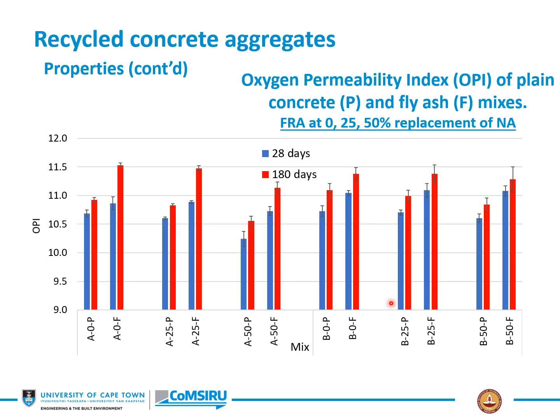If we then look at the OPI, or the oxygen permeability index, of plain concrete and fly ash mixes here, this is actually, again, a fly ash mix with up to 50% replacement. And the OPI is here again. There is a little reduction, but not substantially so. In other words, we're able to make up to 50% replacement here of the natural aggregate and still get very good properties. And again, this can be seen even at 28 days here. Bear in mind that anything with a value over about 10 OPI is actually a very good concrete from a permeability or penetrability point of view.